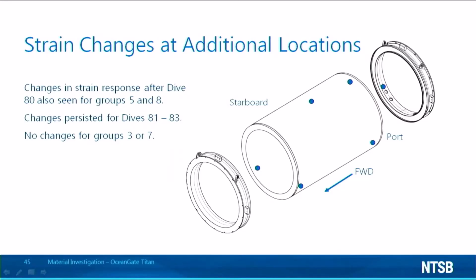So changes in strain response after dive 80 were also seen for the longitudinal strain for gauge group 5 and to a lesser extent for the hoop strain at gauge group 8. Those changes also persisted for dives 81 to 83. There were no apparent changes for groups 3 or 7.